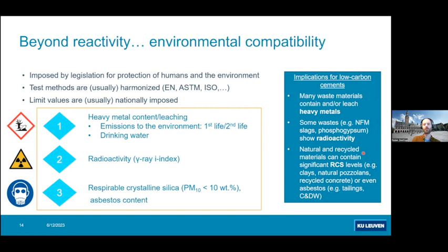And finally, and it's also quite important to follow up on this one, is respirable crystalline silica content, where crystalline silica should be less than 10 weight% in the below 10 micron fraction. That's of course not saying that asbestos is allowed in construction materials. However, we're just saying that in particular in the north, my experience is that some projects show that tailings can contain asbestos, so it's better to avoid them. Obviously, some legacy C&D waste might contain asbestos as well.